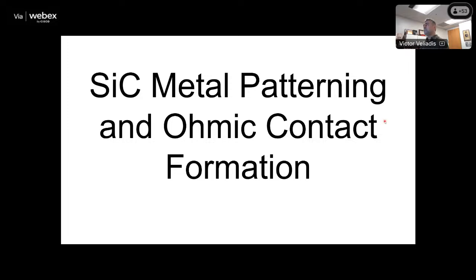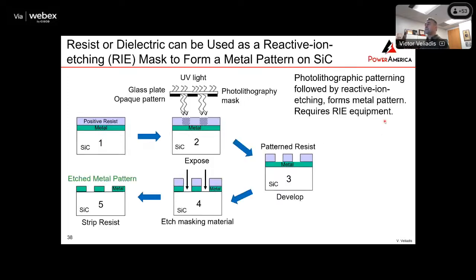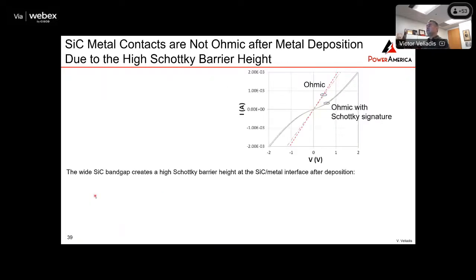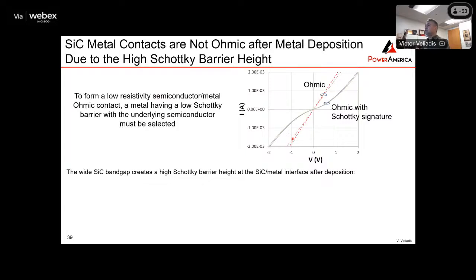Okay, let's look at metal patterning and ohmic contact formation. And I showed the process before where you put metal down and then you use resist to pattern the metal and etch the metal. And that's how you create an etched metal pattern on the wafer. And as I mentioned before, putting metal down on a silicon carbide wafer will not give you a low resistivity ohmic contact that's desirable. It will give you a Schottky contact. You can see here, this has a Schottky signature. And this here is an ohmic contact. And this is because of the barrier height between silicon carbide that has a wide band gap and the metal interface.